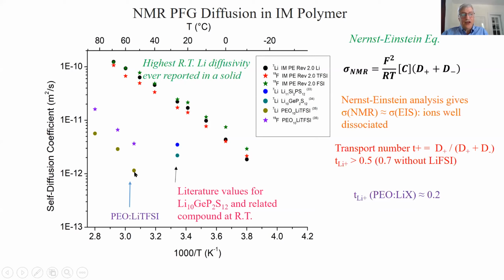In fact, in PEO, it's the counter ion, the anion, that moves faster than the lithium, which you really don't want. You want a lithium-based battery, you want the lithium ions to be carrying most of the current. Here you have the counter ion actually carries most of the current, as in the star over here. Here, the lithium carries at least half the current, okay, as we've indicated over here.